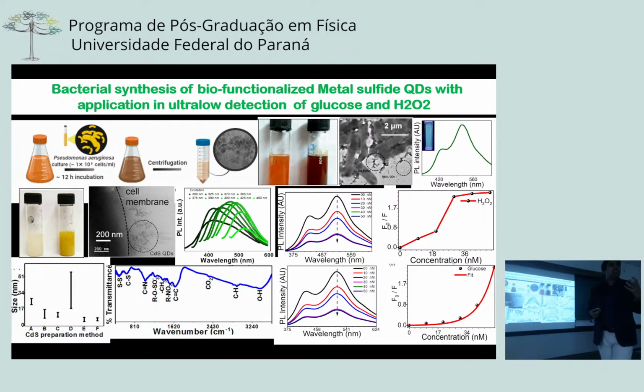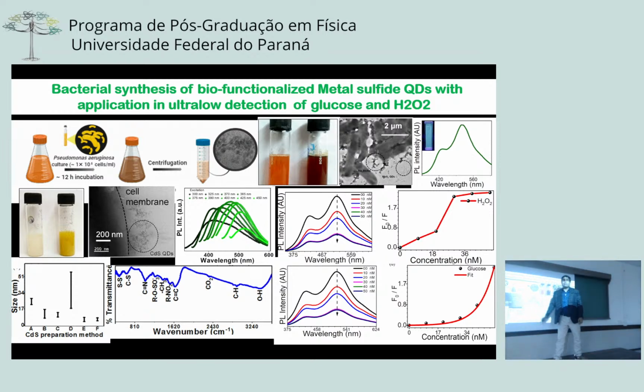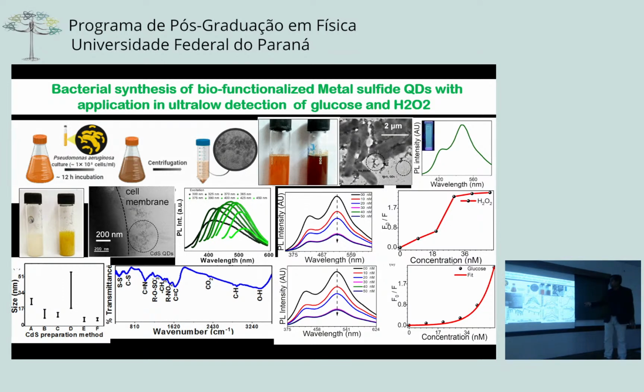Now this dynamics or kinetics of the reaction can be controlled depending on the growth of the cell. You can change the cell growth time, play around with it, and control the dimension and so on. This is a plot which you can see here. These are the distributions of size by different methods, and this is where this naturally grown material shown here has a very narrow size distribution, and the surface characteristics are mostly constant.